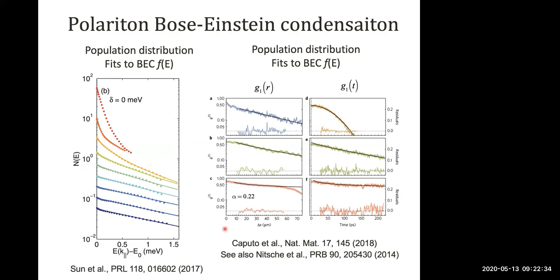So this really reproduces, up to condensation, equilibrium BEC physics very nicely. And more recently, the group of Daniele Sanvitto has also shown that in these same systems, as you increase the particle density, if you measure the value of the first order coherence function in space and in time, in both cases, you find a value of alpha, which is this algebraic decay exponent, equal to about 1/4, which corresponds very nicely to the anticipated BKT type of physics.